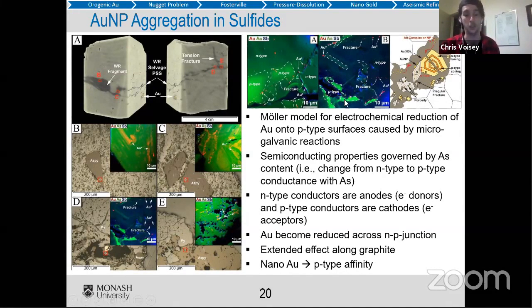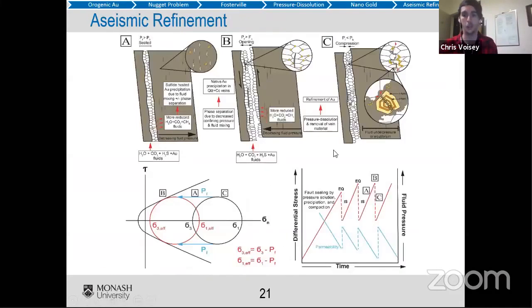So we think during this pressure dissolution, you can actually have additional gold get added to sulfides or possibly remobilize from sulfides by dissolving it. Donating electrons will dissolve the mineral surface. You can free some of that lattice-bound gold, and then you can stick it somewhere else where it likes to hang out, whether that's due to the electric potential or reducing a nanoparticle surface energy, wherever it likes to hang out. It'll go to a favorable site. So if we put it all together, we get the thing called aseismic refinement.